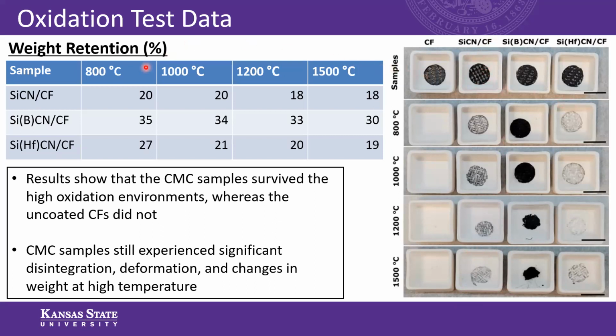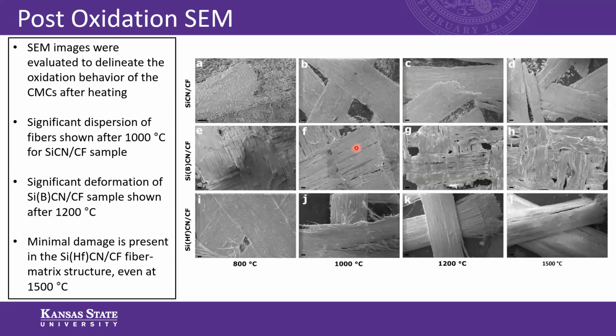And the following weight retention percentages are shown in this table. At 1500 degrees Celsius, the SiCN carbon fiber CMC had an 18% weight retention. The SiBCN sample had a weight retention of 30%, and SiHfCN had a weight retention of 19%. Some SEM images were also taken, and these were mainly done to evaluate the oxidation behavior of the CMCs after heating. In the SiCN case, as you can see, some significant fiber dispersion is shown after 1000 degrees Celsius. For the SiBCN sample, after 1200 degrees Celsius, some significant deformations were shown, and a sort of melting is shown, especially at 1500 degrees Celsius.